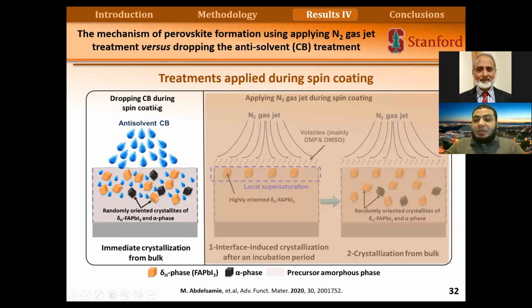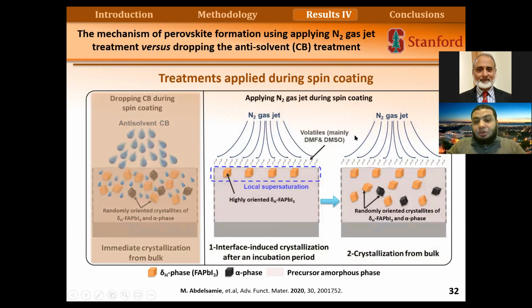So what we understood from the mechanism of this: when we drop antisolvent, because it's an antisolvent, once it's mixing with the solution, it's creating a supersaturation immediately. So we get immediate crystallization from the bulk, and because the antisolvent diffuses into the bulk, we get randomly oriented crystals in the bulk. But nitrogen drying works with a completely different mechanism. The nitrogen itself removes volatiles from the top surface, and this leads to a local saturation of the top surface. And this gives us highly oriented crystals, but these crystals are not the final product. They are from the delta phase.